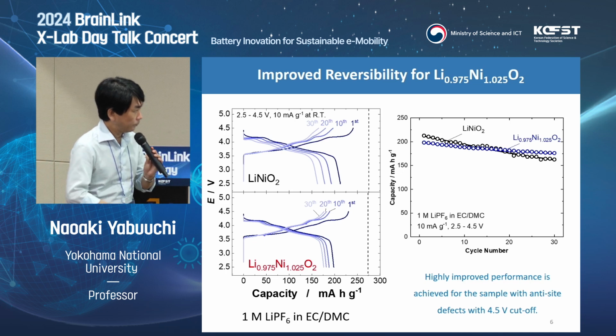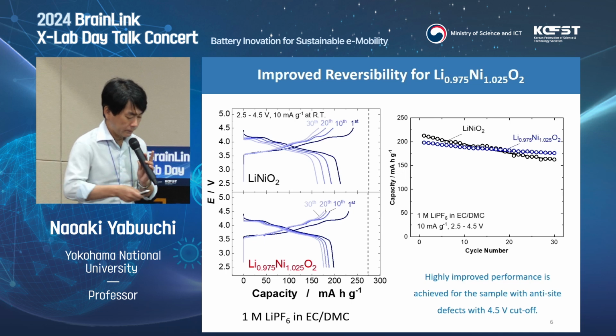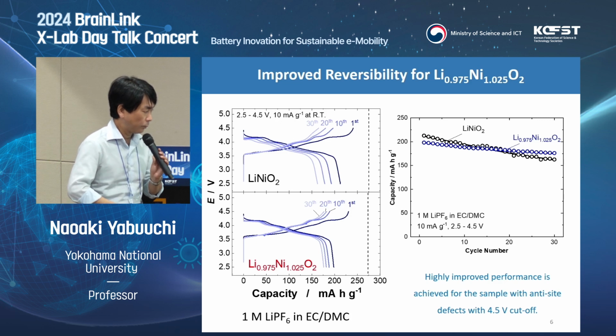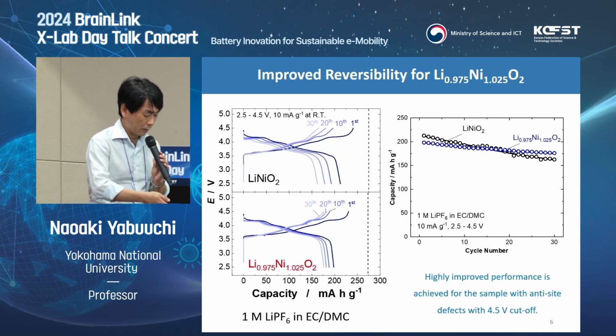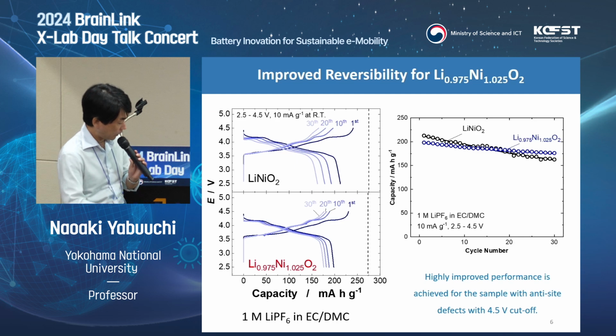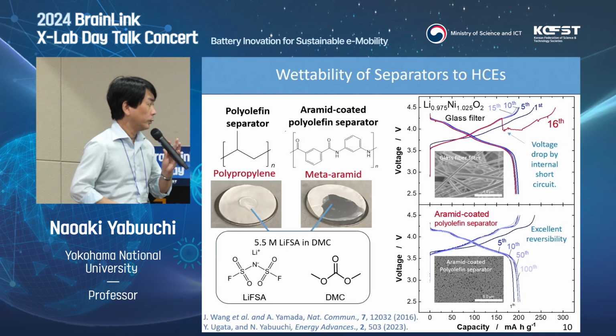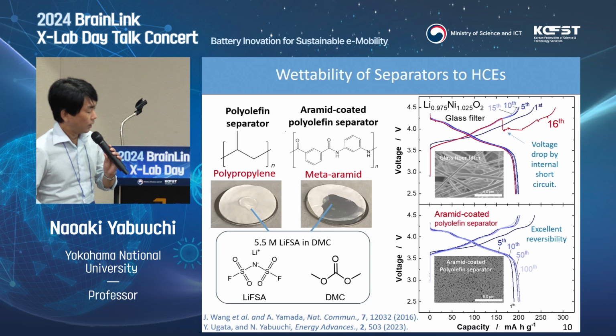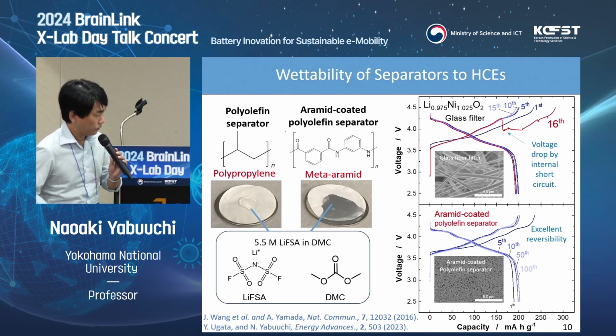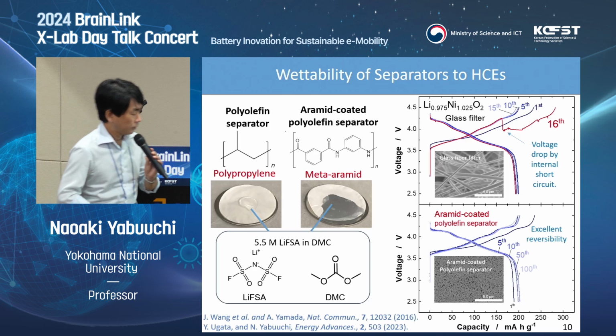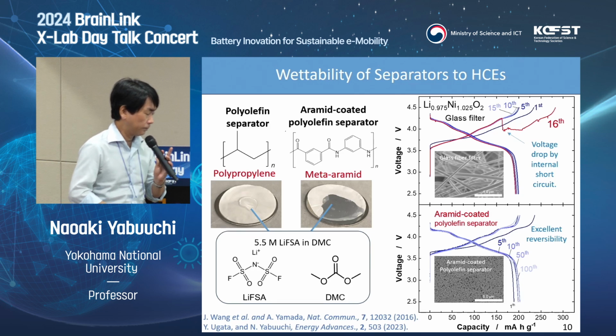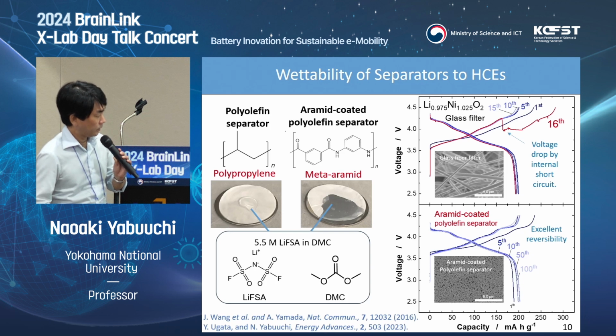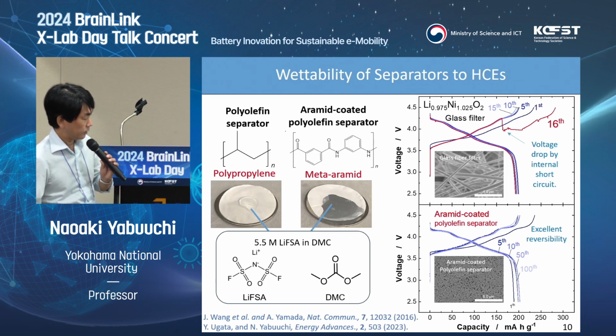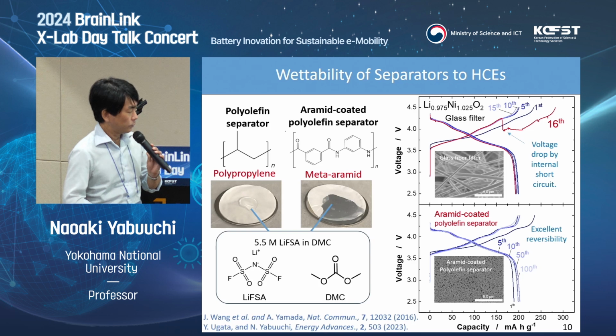The problem of a pure nickel system is that surface degradation is very important. Therefore, the selection of the electrolyte is also a very important parameter. As a model electrolyte, we use a highly concentrated electrolyte solution with lithium FSA. This was reported by Professor Yamada's group in 2016, a very old publication. It is a very simple combination of LiFSA and DMC. However, the concentration is very high, 5.5 molar.